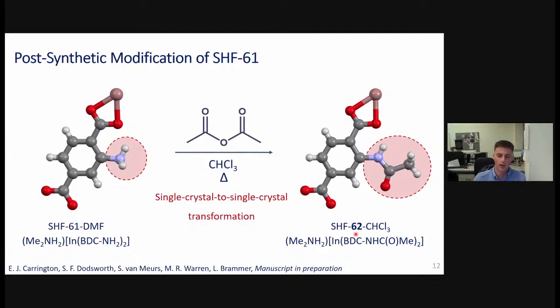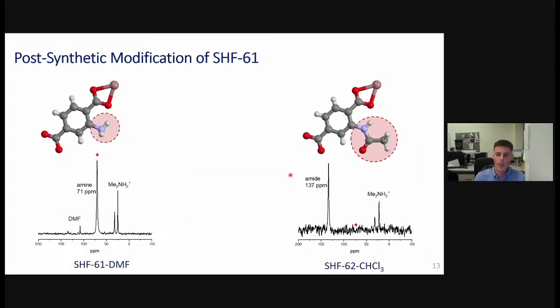And what's really nice about this post-synthetic modification is due to the mild conditions required, you can do this in a single crystal to single crystal transformation, which means we can study the effects of this modification crystallographically. So when we do this, we see that we have a full conversion of this amino group to amide group. So this is modeled at full occupancy at a single site on our carbon ring. And again, we've done the characterization to show this is not only in individual crystals, but this transformation takes place within the bulk phase of the material. So again, we've gone to our solid state N15 NMR, which quite nicely shows the conversion from this amine to amide functional group.